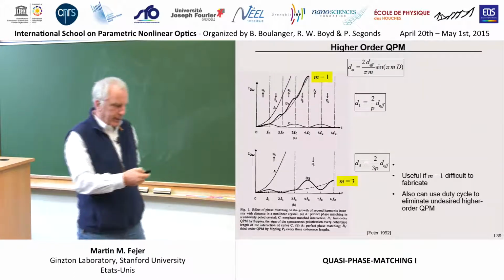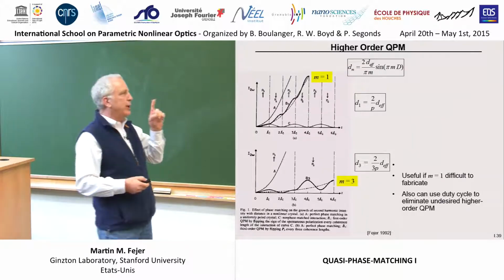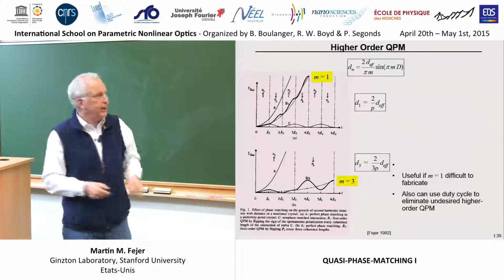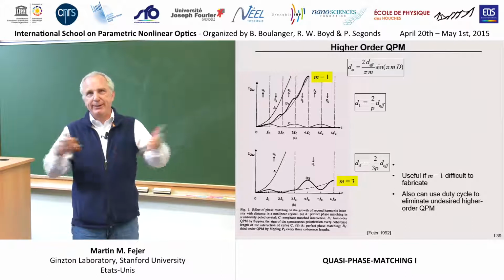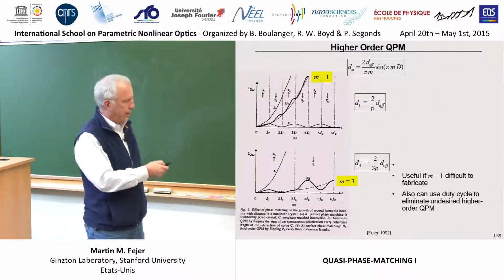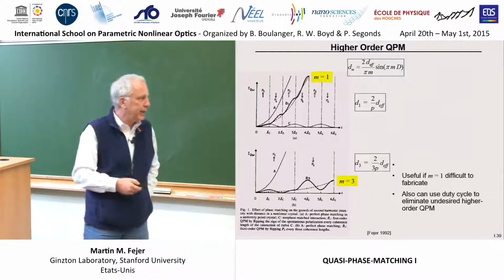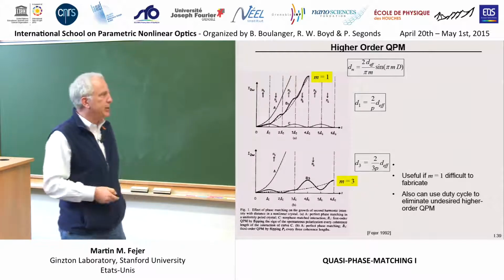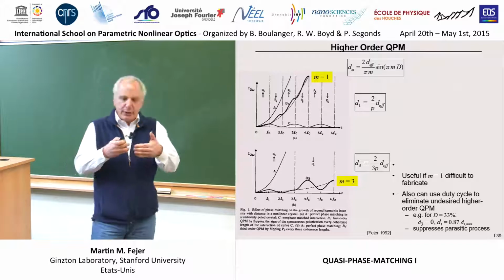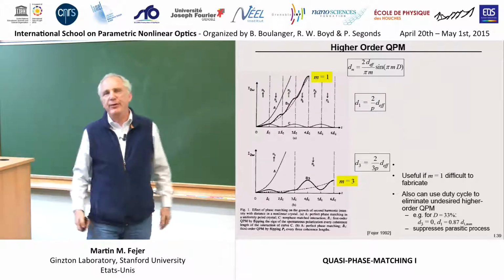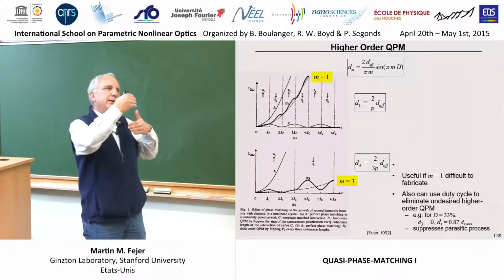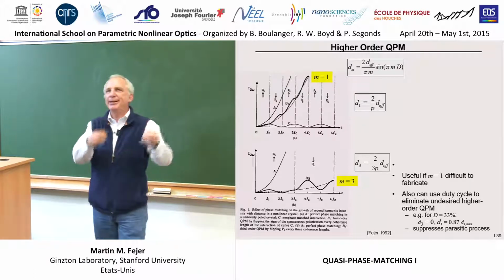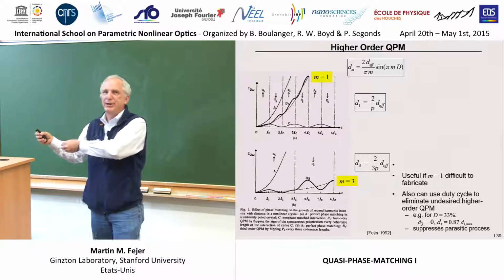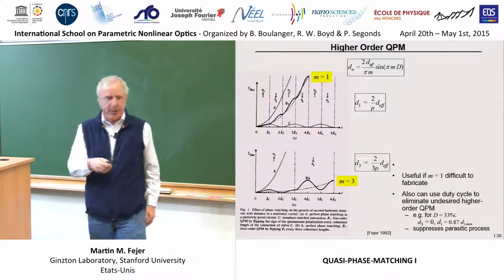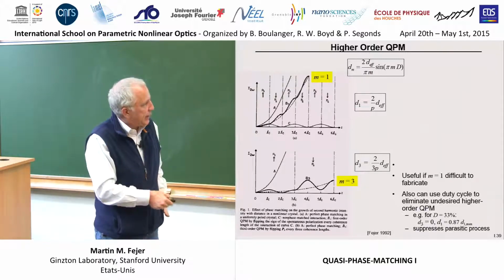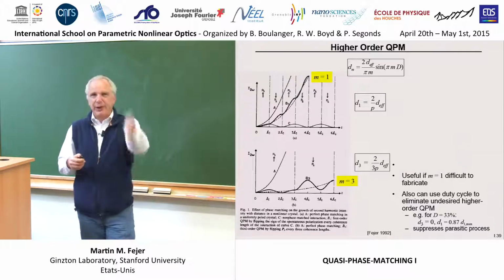And finally, there are 2 reasons you might use high-order quasi-phase matching. One is if it's hard to make a fine enough period structure, you can get away with a longer period if you're using high-order quasi-phase matching. The price you pay is that you're losing nonlinear susceptibility. Another reason you might fool around with duty cycles is sometimes there are parasitic processes. You want to do second harmonic generation of 1.5 micron light to make 750 nanometer light. It turns out that summing 1.5 and 750 to make the third harmonic is accidentally, in lithium niobate, almost third order quasi-phase matched. So you have this other process going on that you wish wouldn't go on. But if you engineer your choice of duty cycle, for example, at 33%, then you exactly zero out that third order Fourier component, and it won't bother you.